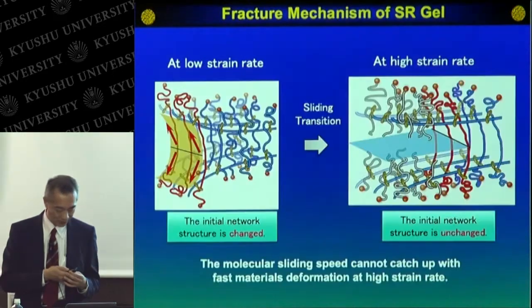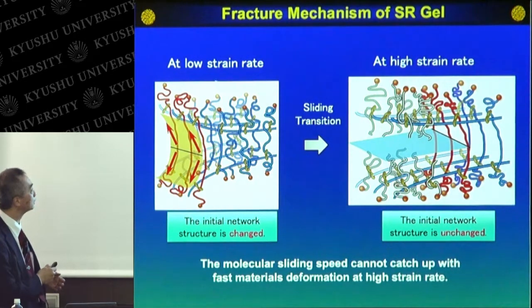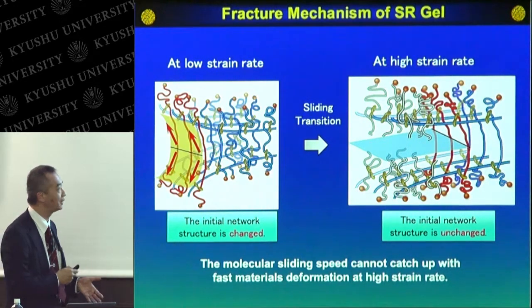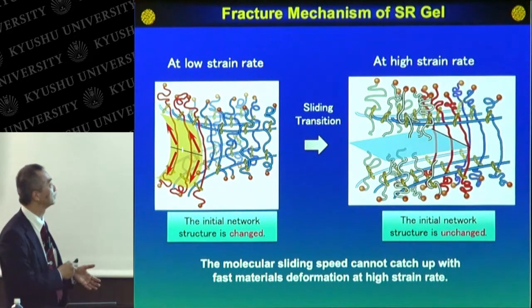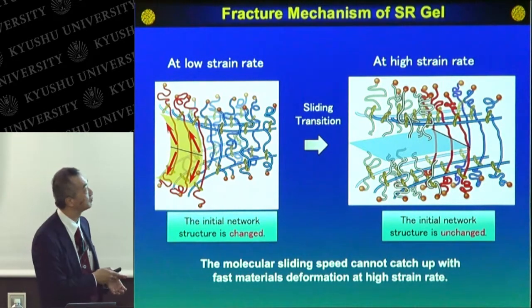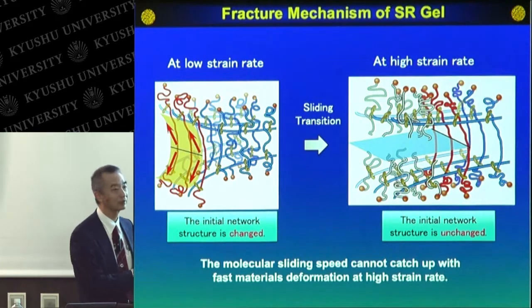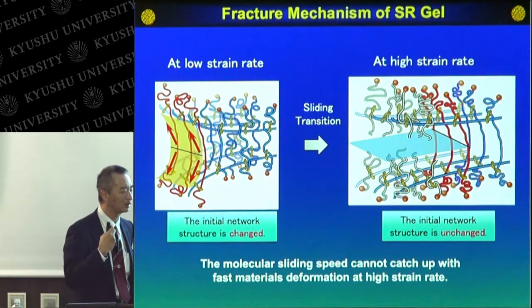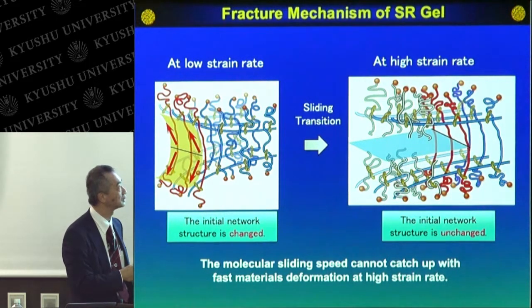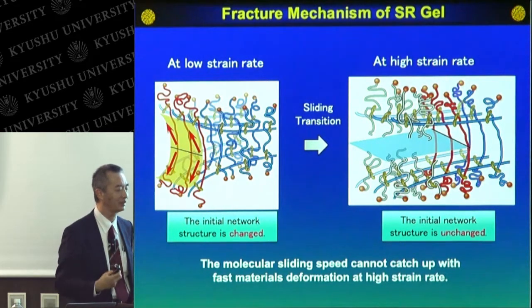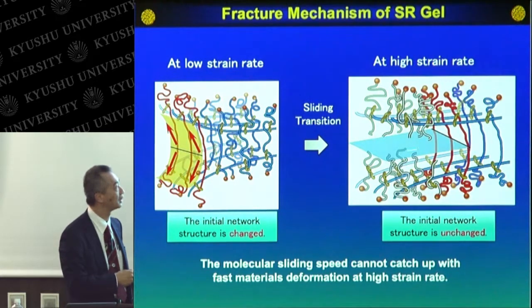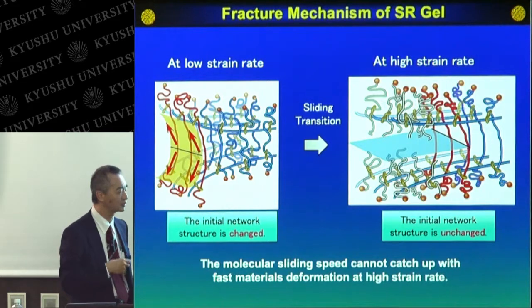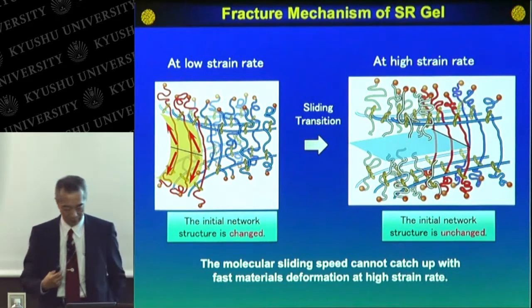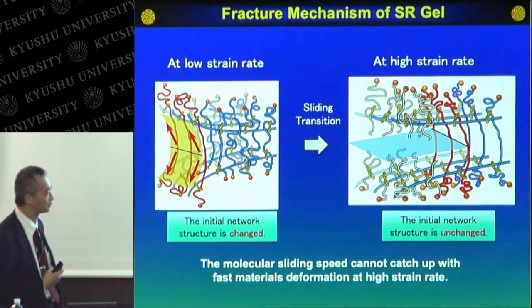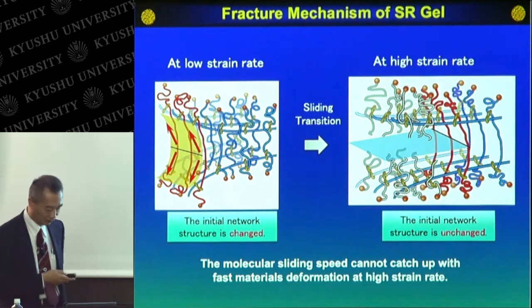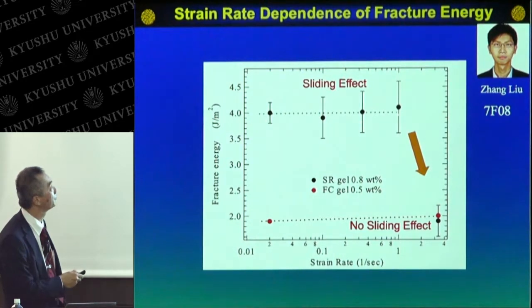This behavior can be explained by the sliding motion of the cross-linked point. At low strain rate, this sliding motion can catch up with the macroscopic deformation. Then it increases the fracture energy drastically. But at much higher strain rate, this sliding motion cannot catch up with the macroscopic deformation. So this slidable cross-linking cannot really slide in the polymer network. So the sliding material shows almost similar brittleness compared to the usual chemical gels. So this shows the strain rate dependence of the fracture energy.